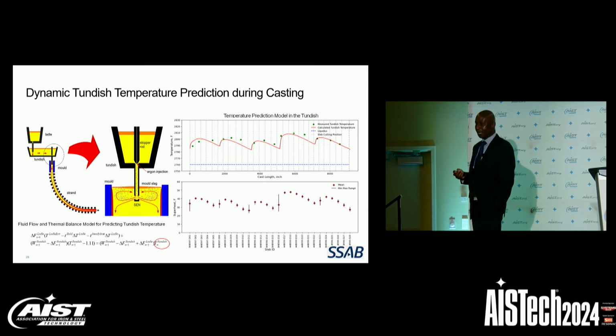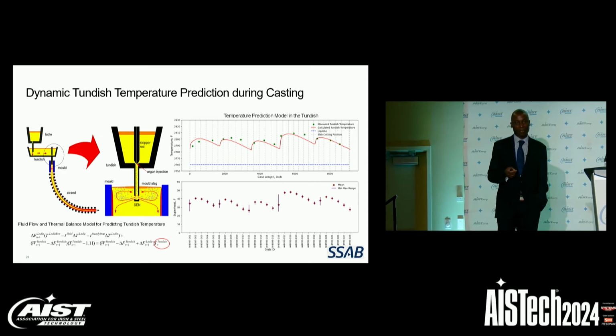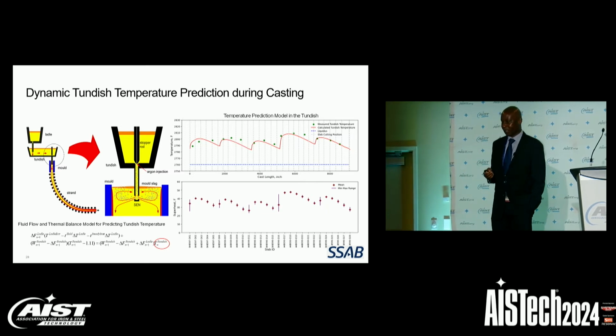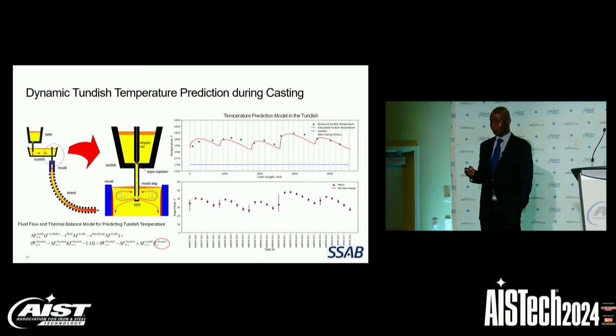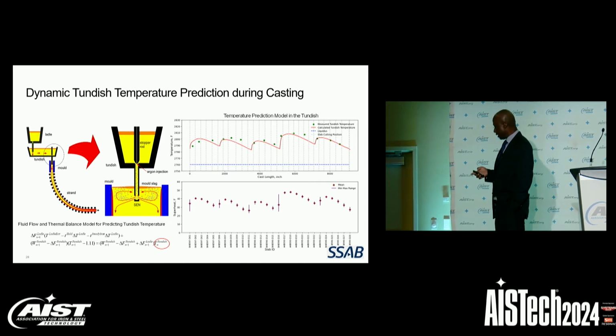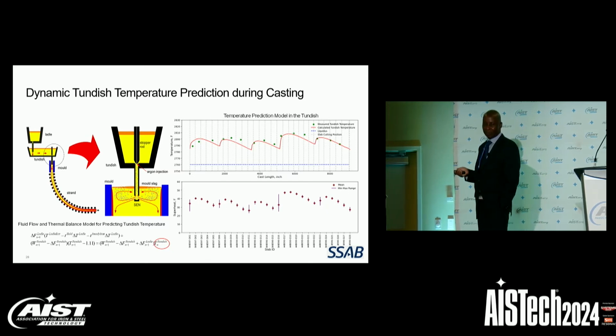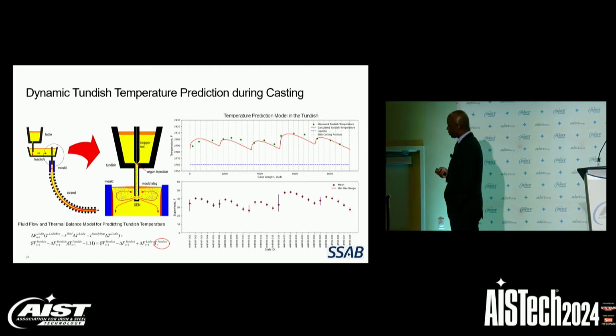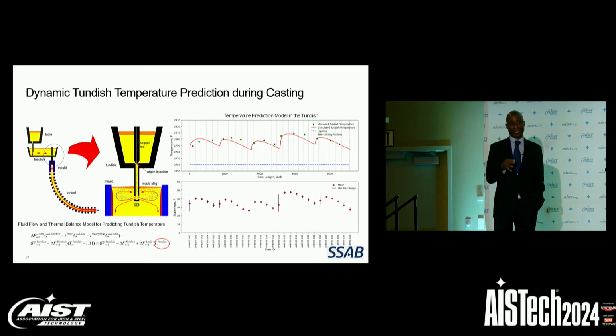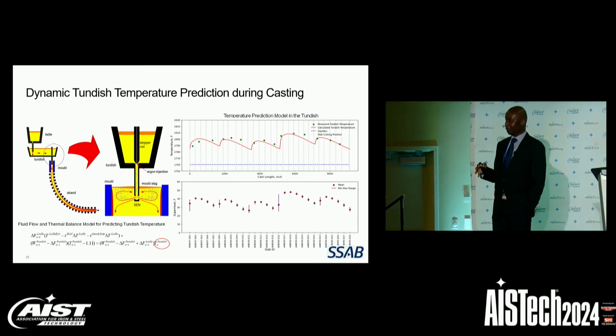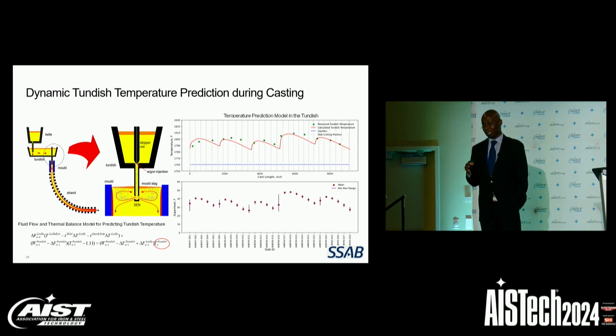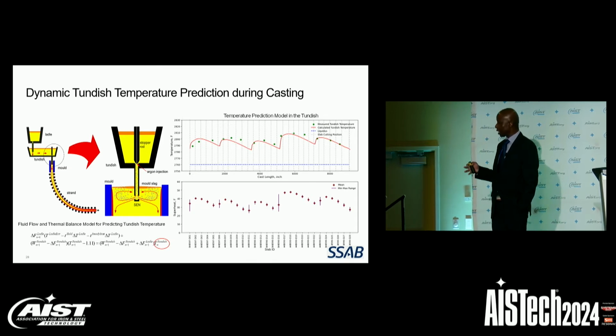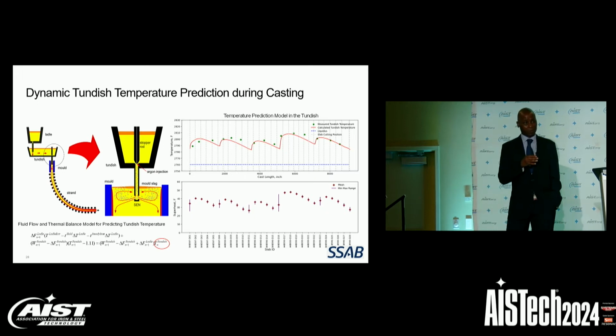So hence, we decided to develop a model to predict temperature in the tundish. The model is based on fluid flow and thermal balance analysis. So the red curve that you are seeing here is the predicted temperature, and the solid circles are the measured temperature. You can see that there's very good agreement between the measured and the predicted temperatures. So what is neat about this model is that for all slabs that are cast in the sequence, we can map out the superheat of all the slabs and then correlate that to the surface and internal quality, and also use that to optimize shipping temperature from the LMF to the caster.